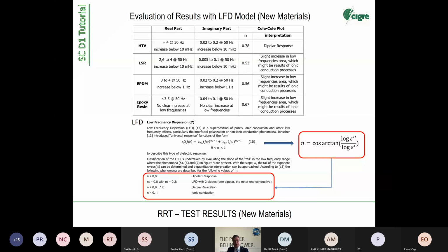And in literature, you find the following values. Normally I explain how you do it. You take this slope. From the slope, you get the angle. From the angle, with the cosine function, you get n. With n, you can look into Jonscher's theory. For example, if you see an n of 0.8, you have a dipolar response. If you see two modes, like here, we have some with two modes, then we have a dipolar response, and the lower one is a conductive response. So it's a mixture of two. So you can filter out different modes of polarization and conduction.